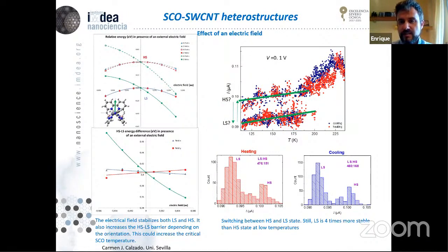We don't have a hysteresis, and what we observe when we cool down is that there is a spin transition, so a conductance transition around the spin crossover transition, but then it's not always in what would be the low spin state; it is actually switching back and forth between what would be the low spin and the high spin state. Still, it is most of the time in the low spin state, almost more than 4 times, but this indicates that indeed the bias may have a role in stabilizing or destabilizing the spin states of the molecule.